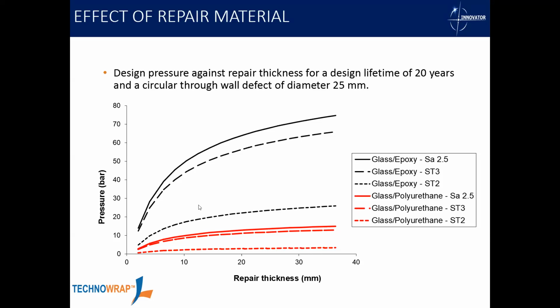And the reason that I say we never like hand prep is that the lower black dotted line, for the same repair thickness, you may be getting 15 bar pressure retention. So you're seeing a massive reduction, probably 80% reduction in adhesion, just due to the level of surface prep you're achieving. Obviously we want these repairs to be done properly. Some of them are on safety critical lines. So clearly you want a high level of adhesion, which is why I would always push for the sandblasting or the bristle blasting.